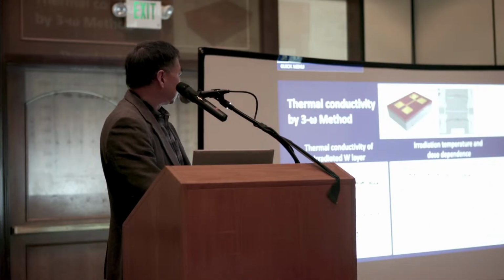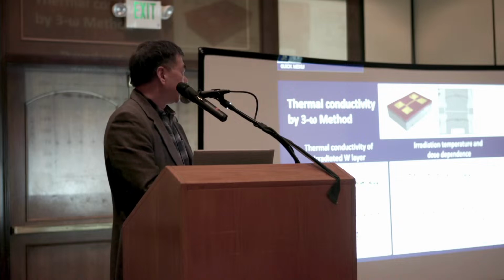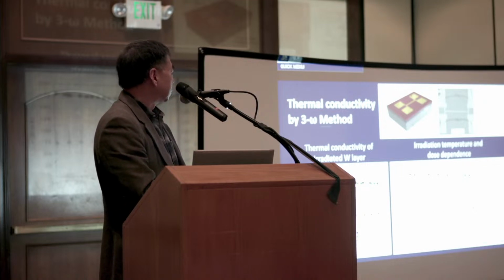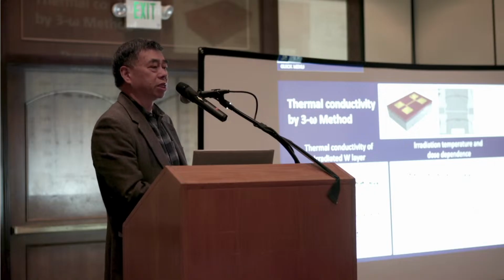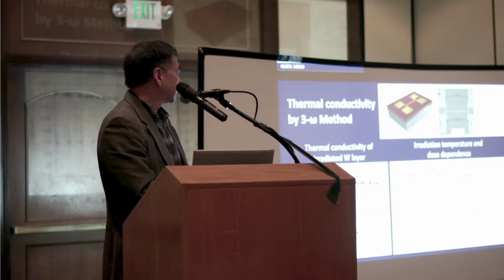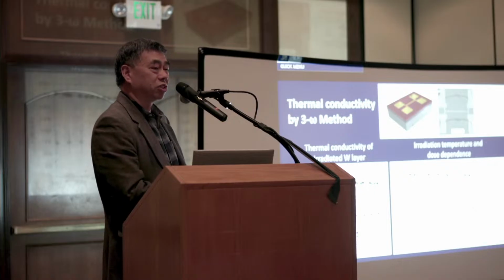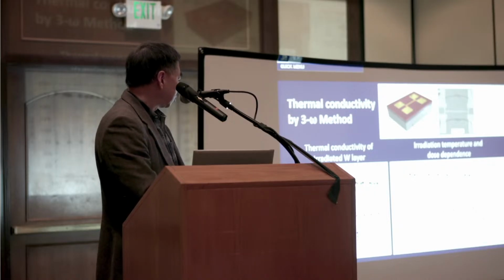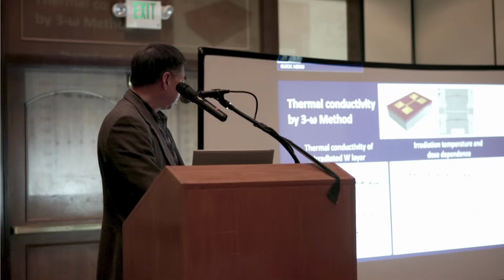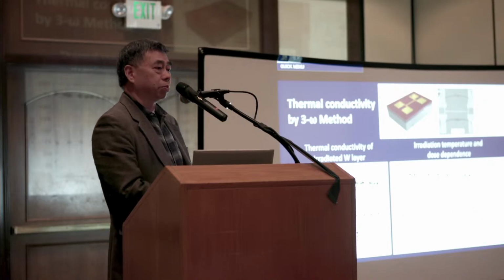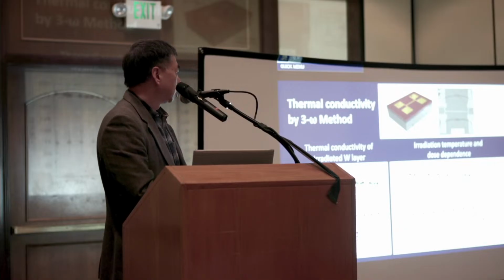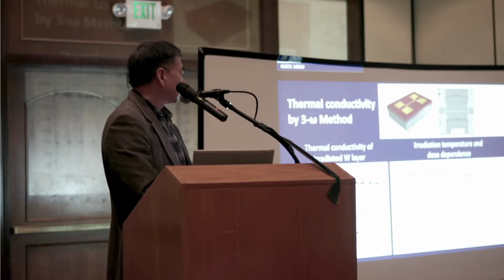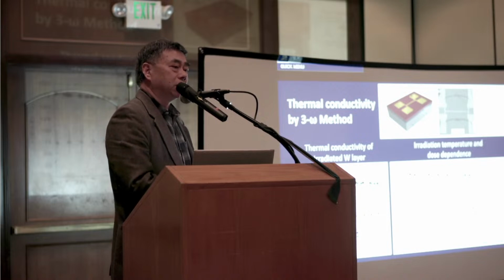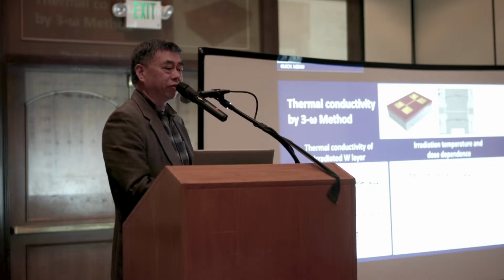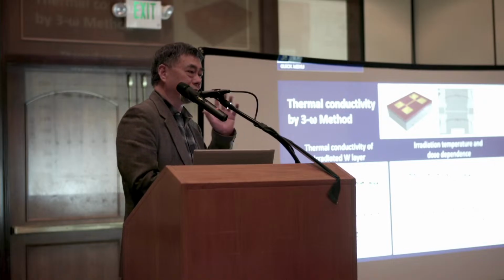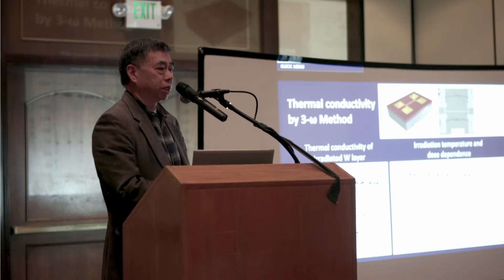So after the damage, you can look at the thermal conductivity. We had to use a very surface-sensitive technique, a 3 omega approach, to look at the thermal conductivity change in the damaged tungsten, because the ion damage range is relatively shallow. And you can see even with very little damage, about 0.2 dpa, the thermal conductivity drops by more than a factor of 2 already. We also tried different irradiation temperatures, but the damage recovery was not significant, just because tungsten is such a high temperature material. We have to go much higher to be able to remove the damage.